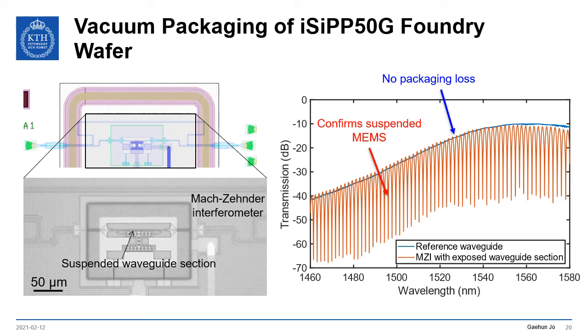On the left, you can see the device we used, which is a Mach-Zehnder interferometer underneath a sealing cap. In the short arm, we also included a suspended waveguide section. After sealing, we could access the device optically with grating couplers just outside of the cap. On the right, we show the measured transmission spectrum from 1460 to 1580 nanometers.